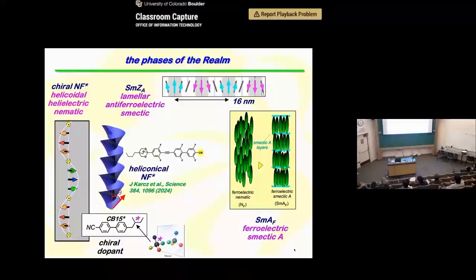Okay, and then there's another new phase where you have this, and layers just form. So you end up with two sets of layers, a set of horizontal layers, and then this set of vertical layers in the same phase. Okay, so then you can imagine combining this smectic A with twist. So what happens if you put chiral doping in the smectic A phase?